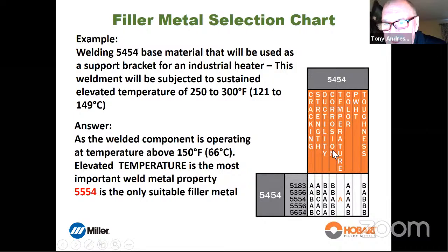So in this case, temperature is most important, and there's only one filler alloy that has a rating for welding this base material to this base material for temperature applications, and it is 5554. And 5554 was designed specifically for welding 5454, and it has a maximum amount of 3% magnesium, so it doesn't become subjected to stress corrosion cracking or sensitization.